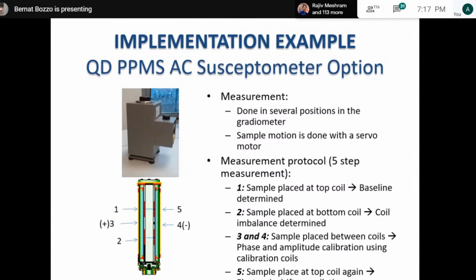This sample is placed at the end of a sample rod, and the other side of the sample rod is connected to a stepping motor, with which we can move the sample up and down for several reasons. First, to center the sample with millimeter accuracy, and secondly, to perform a more sophisticated measurement protocol, which makes our results more accurate. Basically, this measurement protocol is what we call a 5-step measurement. The first step is to place the sample at the top coil, apply the field and measure, then we place it at the bottom coil and repeat the same. The difference between one measurement and the other lets us evaluate the slight difference we can have between the top and the bottom pickup coil, which ideally should not exist, but there could be.